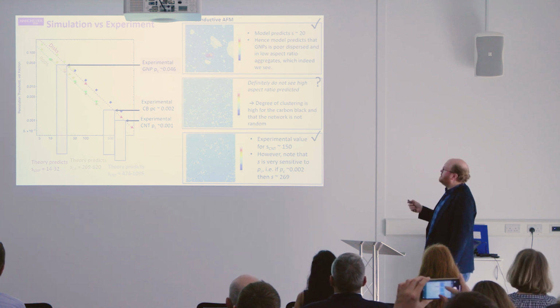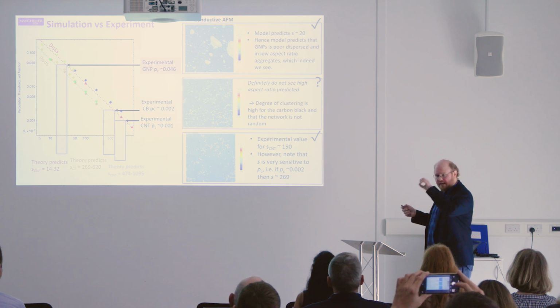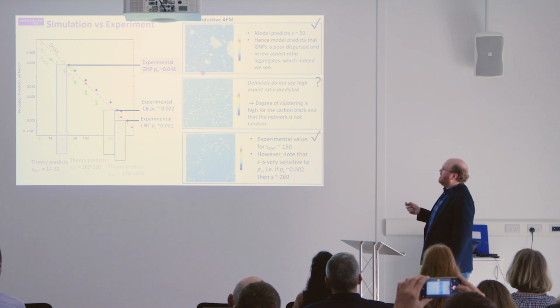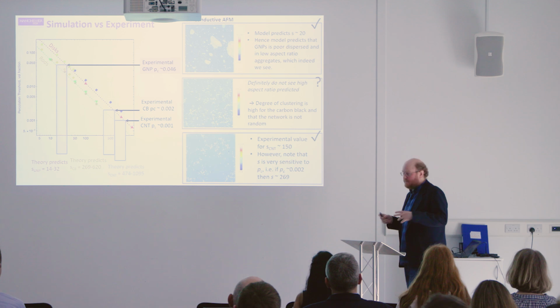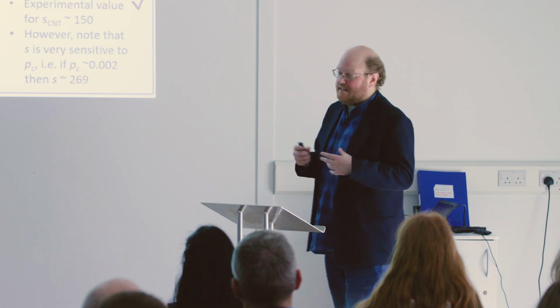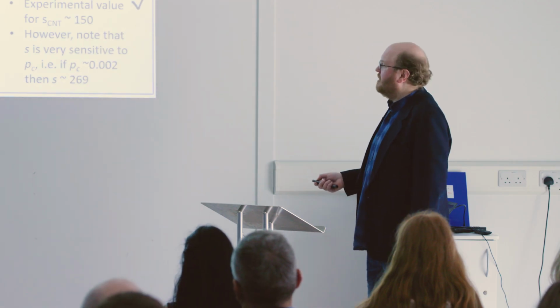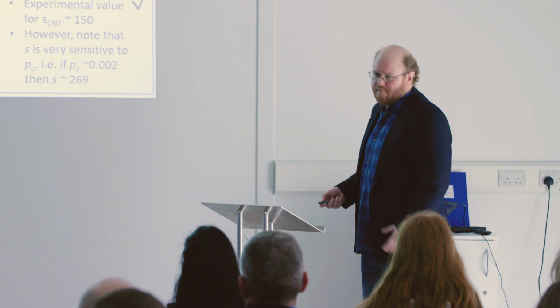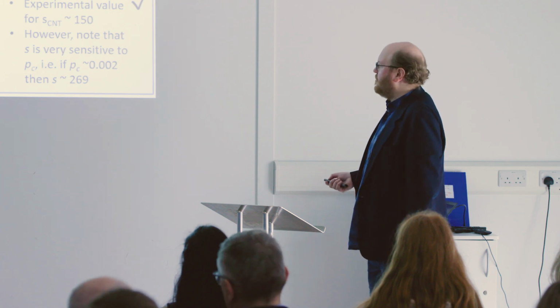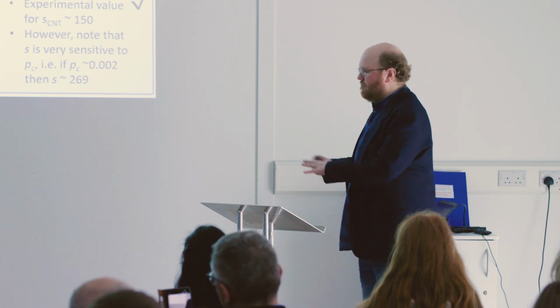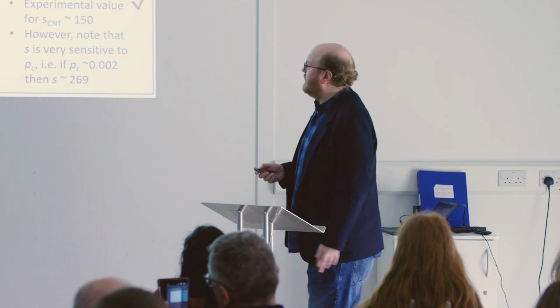These conductive AFM images show you've got these essentially isolated conductive islands that are not in contact with each other because there's no connected pathway. And so that's why you need, again, a much higher loading. The nanotubes have a very high aspect ratio, over 150. So these disperse much better, and again, are much better connected.